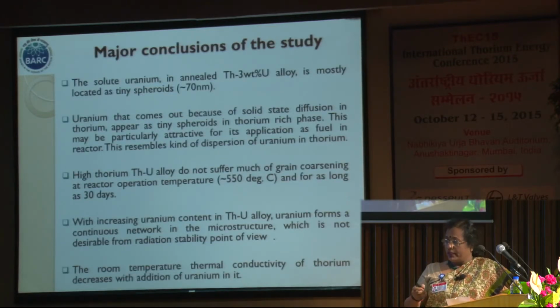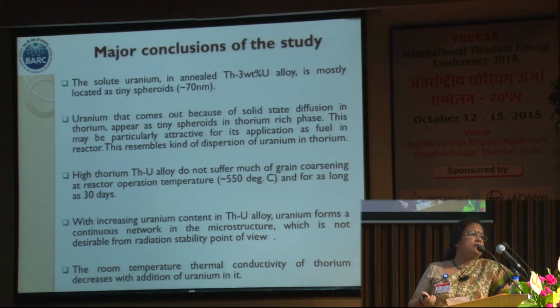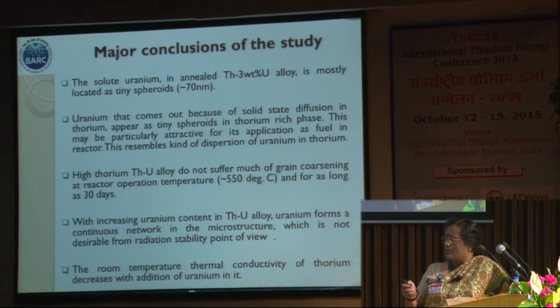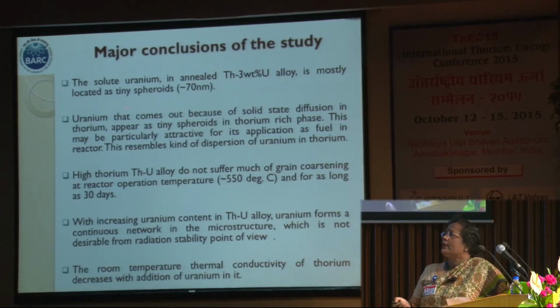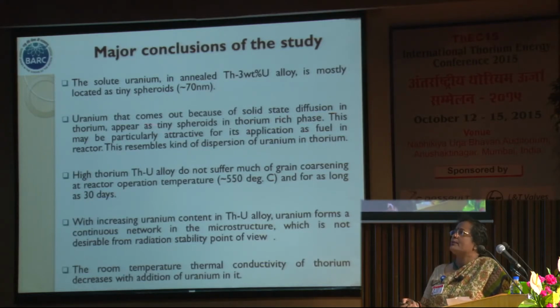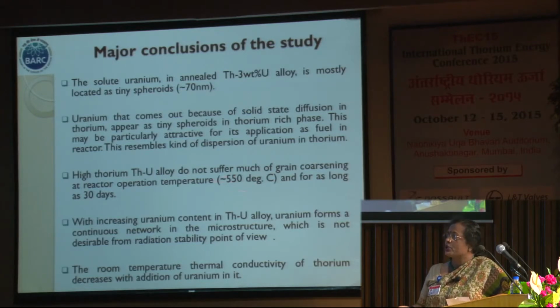Based on that, we have drawn a few conclusions which can be checked by our fuel fabricators to select a composition. Here we see that solute uranium in annealed thorium 3 weight percent uranium alloy is mostly located as tiny spheroids around 70 nanometer. The uranium that comes out because of solid state diffusion in the thorium appears as tiny spheroids. High thorium uranium alloys do not suffer much grain coarsening at reactor operation temperature. This means these compositions were kept for as long as 30 days at this temperature to see whether there is any grain coarsening effect.